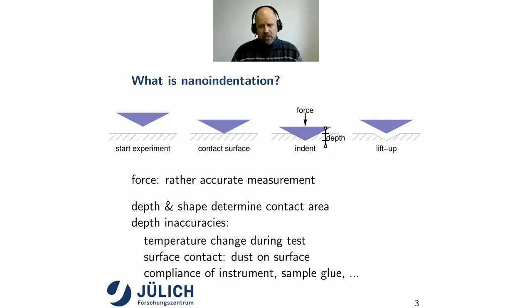If we now look at these measurements, the force measurements are rather accurate. I mean, there's some scatter on it, but that's just normal scatter. The depth and the shape of the indenter are a little bit more correlated. So if you measure the depth and know the shape precisely, then you know the contact area. But the shape of the nanoindenter tip changes during your experiments over the months, and also the depth has some inaccuracy because you have the temperature change during your experiment, which leads to drift. You have to identify the surface contact very precisely. Basically what happens if you have a little bit of dust on the surface, and you have instrument compliance, so sample, glue, how well you screw your tip into the holder.